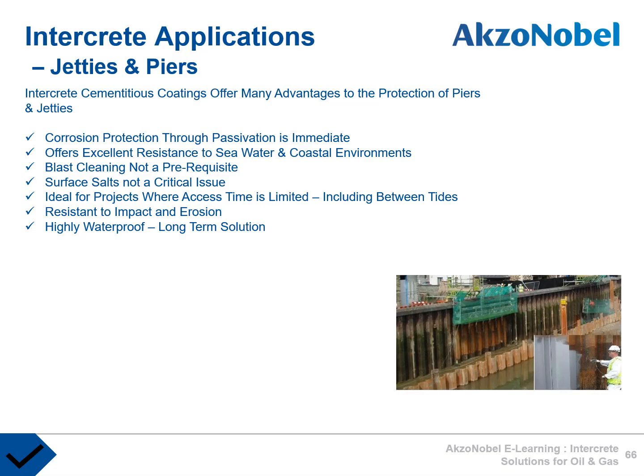Intercrete cementitious coatings offer many advantages for the protection of piers and jetties. Intercrete 4840 works very differently to conventional systems. Again, immediate protection through passivation, unaffected by salt water. Blast cleaning is not necessary, and this is a big advantage, as one of the biggest challenges in protecting tidal areas is not having sufficient time to prepare the surface sufficiently. Intercrete 4840 is robust and resistant to impact, and is particularly effective in preventing rust creep if breached. Intercrete products provide long-term solutions for immersed and semi-immersed assets, with exceptional waterproofing from just 2 millimeters of thickness.